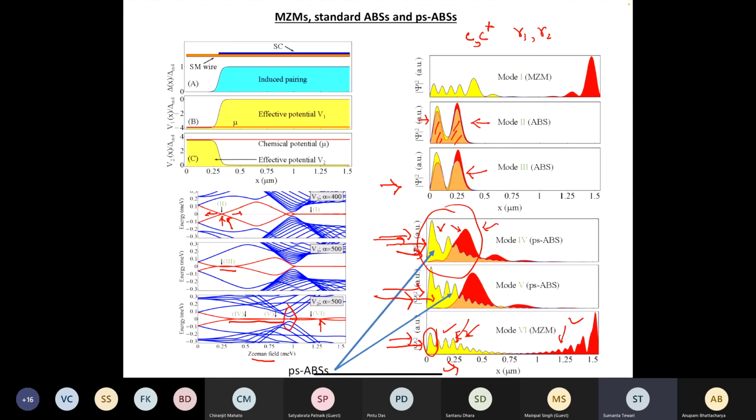Right? So gapless surface states, those Dirac cones that people see in ARPES experiments. The bulk is gapped. You see the gapless surface states, and if you have an odd number of Dirac cones, then you call it a topological insulator. This situation is exactly the same. Topological insulators have gapless fermionic surface states. Topological superconductors have gapless Majorana fermionic surface states. So if you do not see gapless surface states, it is very hard to claim it's a topological superconductor.